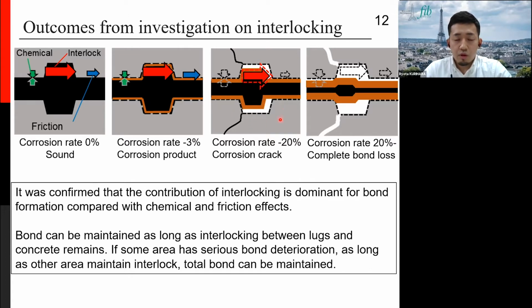After the corrosion crack, the corrosion product can leak from the crack, so a gap between rebar and concrete is generated. In general, the bond is often assumed to be lost in this state, but the interlocking effect can be maintained because the contact between lugs and concrete exists, according to this research. When the contact is completely lost, or when concrete around the rebar is fractured, significant bond loss occurs.